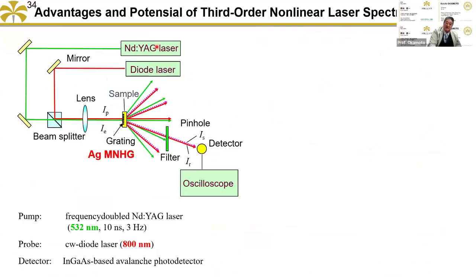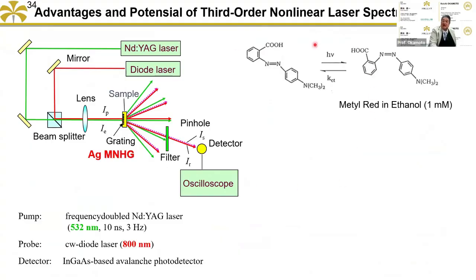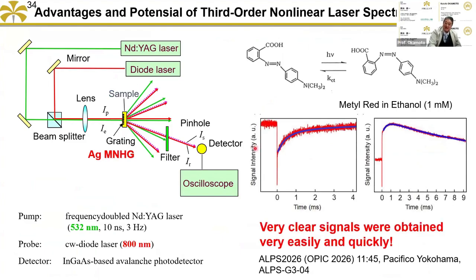Then we tried to form the spectroscopy using a frequency-doubled Nd:YAG laser for the excitation beam and a diode laser for the probe beam. We tried to detect the molecular dynamics of methyl red in ethanol. We just formed this structure. Usually nonlinear spectroscopy is very difficult to tune, but just one time, easily, we can obtain the signal of the molecular dynamics. That's the free molecular dynamics in the solution, and the slow processes are probably the interaction of the metal nanoparticle and the molecule. Easily we can monitor the molecular dynamics by this method.